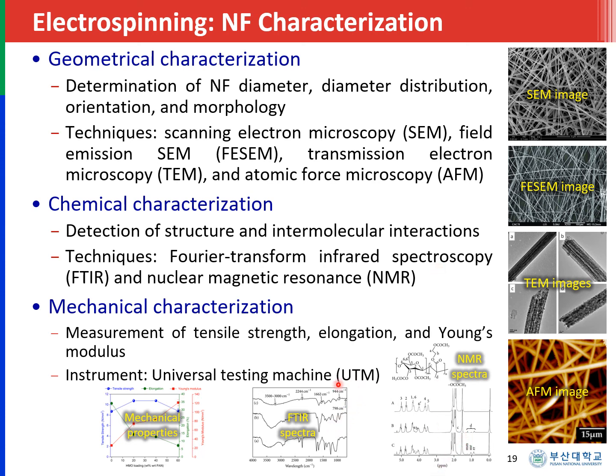So, for FTIR analysis, this is a sample result. You can get this kind of peaks which correspond to particular functional groups. And this is a sample of an NMR spectra, and it would also show you the functional groups present in your polymeric nanofibers. In mechanical characterization, we will be able to measure the tensile strength, elongation, and Young's modulus.